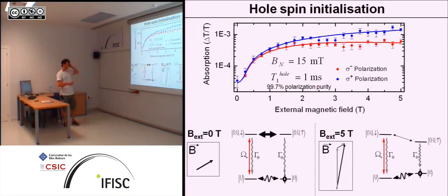Well, what we can do is we increase the external magnetic field. The overall magnetic field of the nuclei doesn't have any preferred orientation in space or in direction. So let's assume it's 45 degrees. So that means you always have a big XY component the electron spin can couple to, and that leads to this electron spin precession. So that means that you have a strong coupling of these excited states and fast population transfer, which you need to populate this state with only this laser.